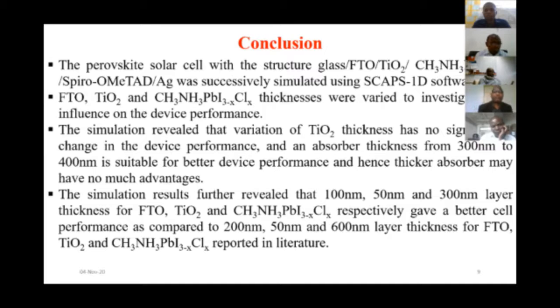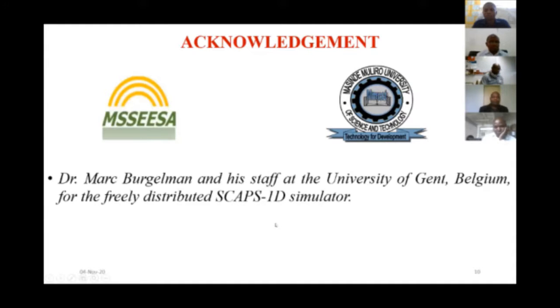In conclusion, the simulation revealed that the variation of TiO2 thickness has no significant change in the device performance, and an absorber thickness from about 300 to 400 is suitable for the performance of the cell. Hence, a thick absorber layer may have no much advantage. The simulation results further revealed that 100, 50, and 300 nanometer layer thicknesses for FTO, TiO2, and CH3NH3PbI3-xClx respectively gave better performance than the 200, 50, and 600 nanometer thicknesses we were comparing with, which have been reported.